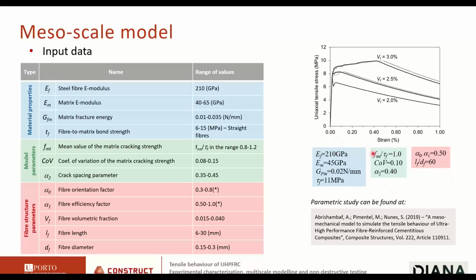So using this set of data that I showed here, you see what the outcomes of the model are for instance, for different fiber contents, okay? You see that for a given fiber content, you have different curves. So don't forget that every time we run the model, we have a random distribution of the matrix tensile strength. And for instance, different runs will lead to slightly different results, mostly on the crack formation stage.